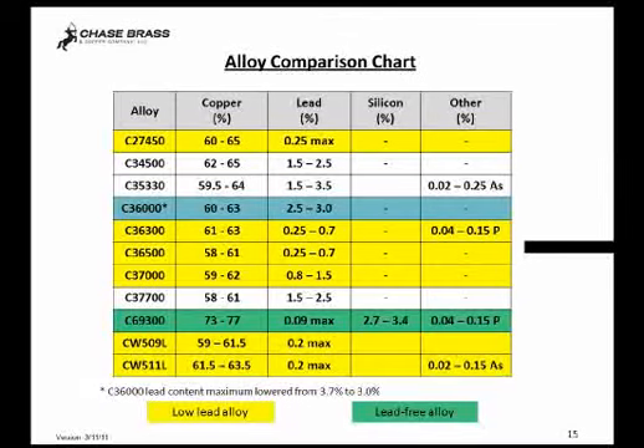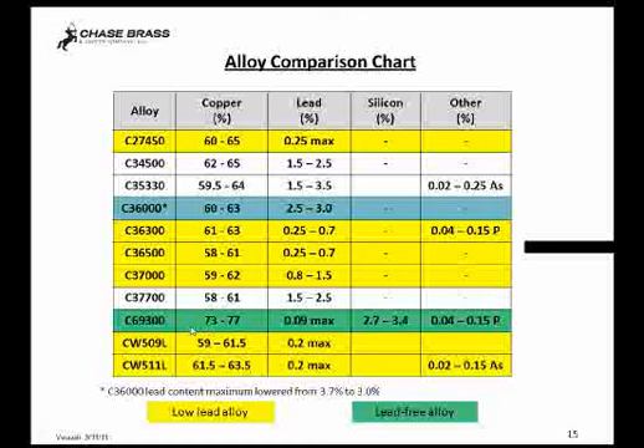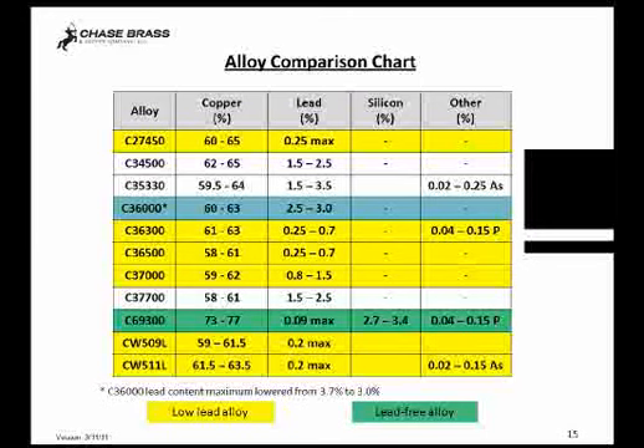There are some dezincification-resistant alloys in this table, 35330, which contains arsenic and has a relatively low zinc content by virtue of the higher copper level. There's a European alloy, CW511L, which contains arsenic. There's a 693 alloy, which contains phosphorus. Alloy 363, which contains phosphorus. And potentially those alloys can be used in some of these NSF-14 controlled applications.